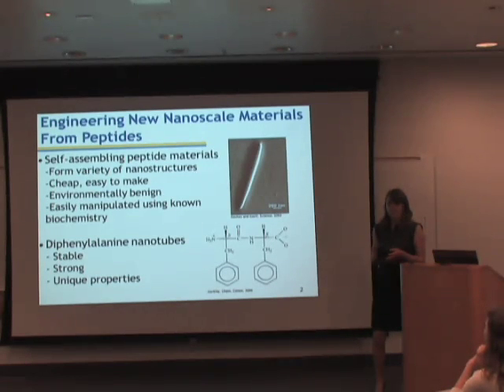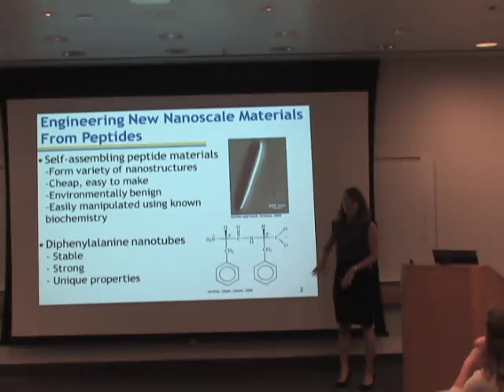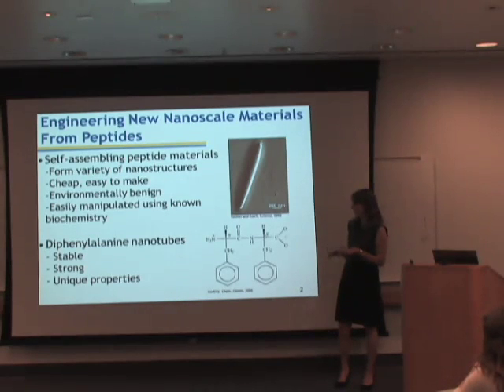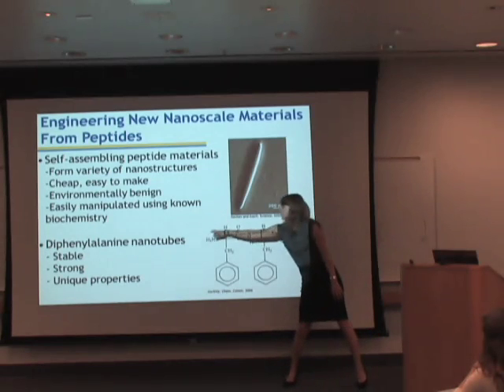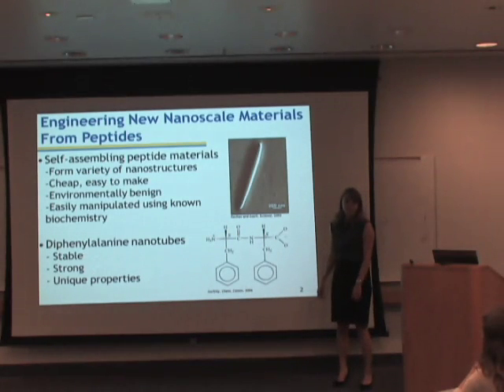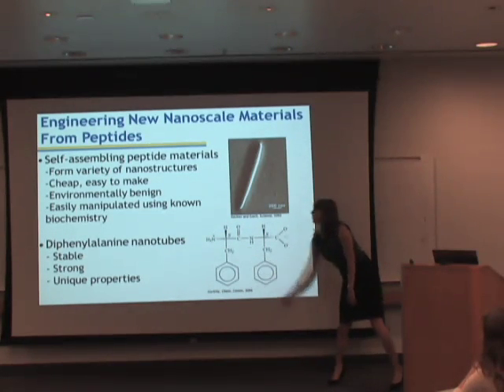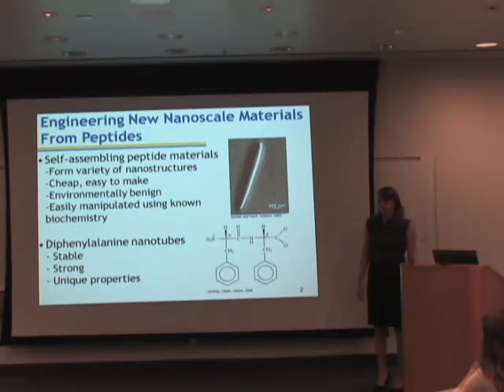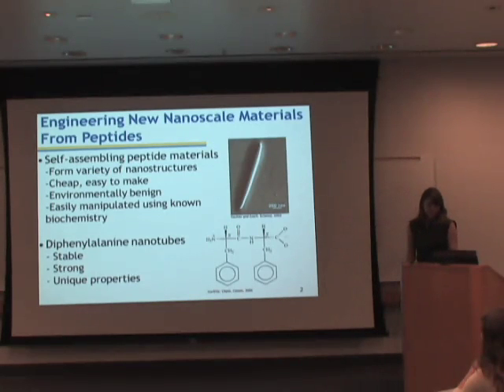Diphenylalanine is one of the first peptides that exhibited this self-assembling behavior, and its molecular structure is shown here on the bottom. The only thing you really need to know about this molecule is it is amphiphilic. That is, it has both polar charged groups here and here, and nonpolar hydrophobic groups here and here. When placed in water, diphenylalanine forms nanotubes, as shown in this SEM image above. These nanotubes are stable, strong, and have many unique properties, including photoluminescence and strong piezoelectric activity.